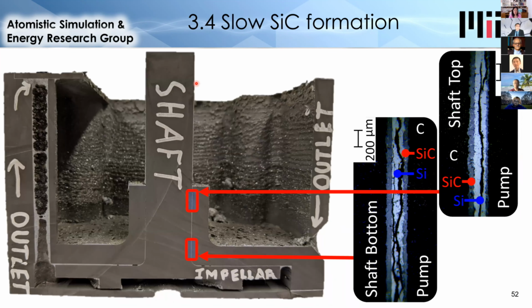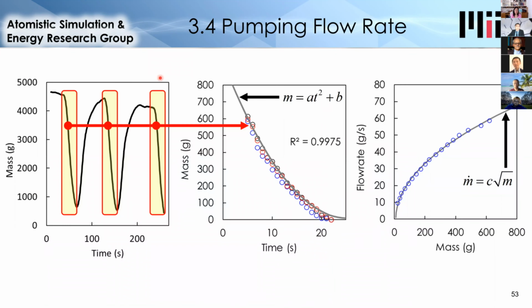So in later experiments, we just made the sleeve of the pump shorter so that it could be fully immersed in the silicon. And this prevented the shaft from binding. So with these experiments pumping silicon, I was able to measure the flow rate just as I did with water. On the far left are the experimental drain curves. The center figure is just those three plotted at the same time. And then numerically differentiating and plotting mass versus mass flow rate, I was able to get this final curve, which again fits well to the square root behavior expected. And so when I measure the mass of the pump, I can determine its flow rate.